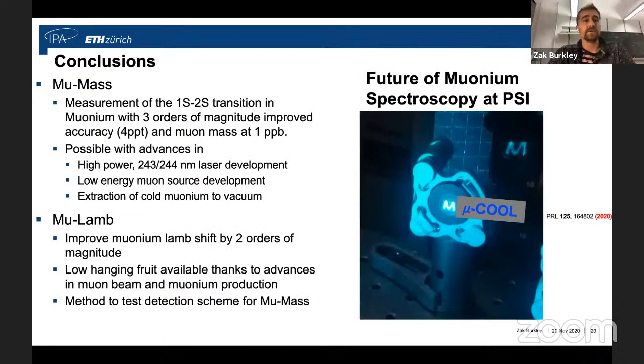With that, I'd like to conclude that we're actively working on the MuMass measurement here, the 1s-2s, and in a couple of weeks, we're going to try this first CW excitation of the 1s-2s transition in muonium. The long-term goal of this measurement is to measure this transition with a 3 orders of magnitude improved accuracy and get the muon mass at 1 part per billion. And this is possible with advances that we've shown in these high-power deep UV lasers, low-energy muon source development, and extraction of this cold muonium to vacuum.